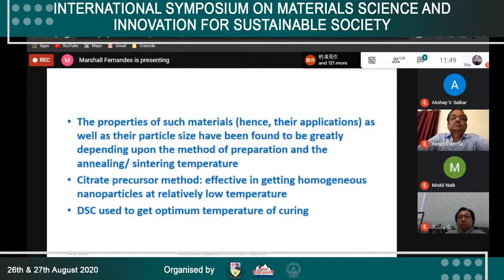So what is happening upon different heat treatments, annealing, sintering, or heat quenching, and what impact does the period of heating have on the property of the particle? The size of the particle is very important. So these are standardized using the citrate precursor method, and the citrate precursor method is very effective in getting homogeneous products. Homogenization is very convenient here, and at relatively low temperature, the nanoparticles could be prepared.